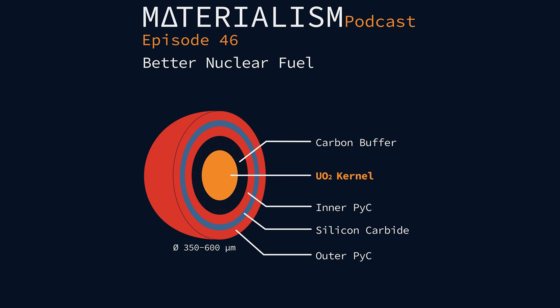From there, they'll put these into a fluidized bed chemical vapor deposition process. So fluidized bed, basically all of these different uranium kernels are floating in a gas, in the sense that they're suspended and not making contact with any sort of substrate. The flowing gases are typically argon or hydrogen, depending on which coating you're doing. And by varying the concentration of the gases and the temperatures at which they're reacting, they can control the microstructure of what gets deposited on there.